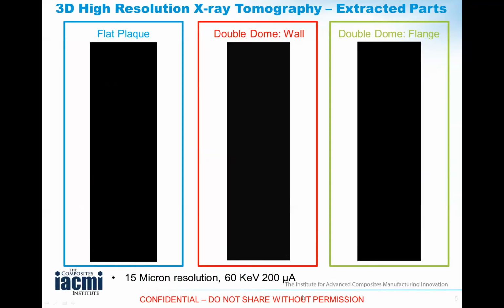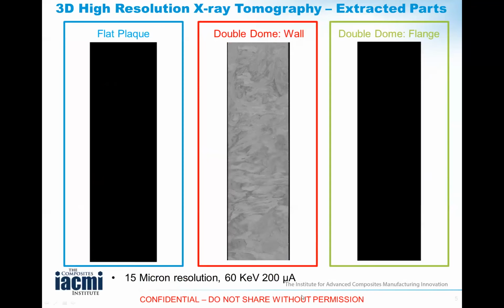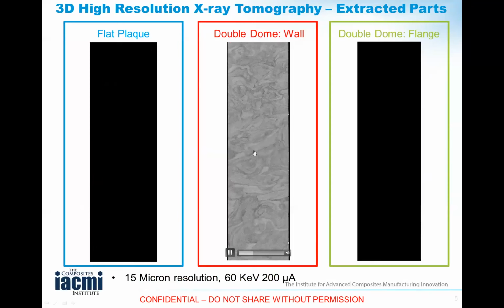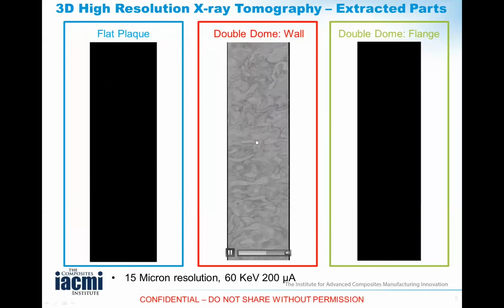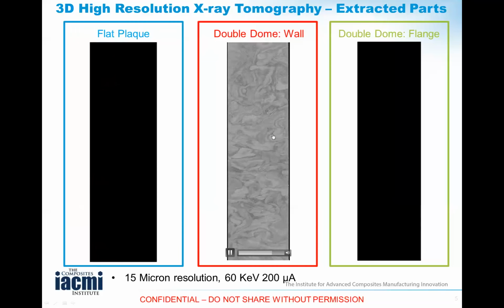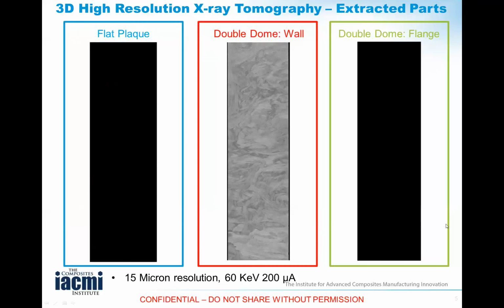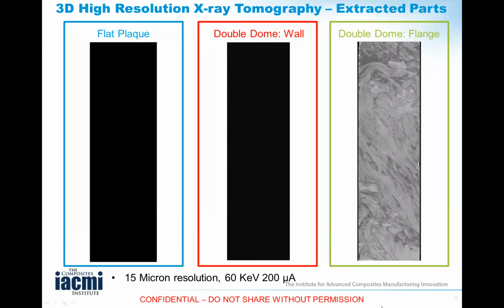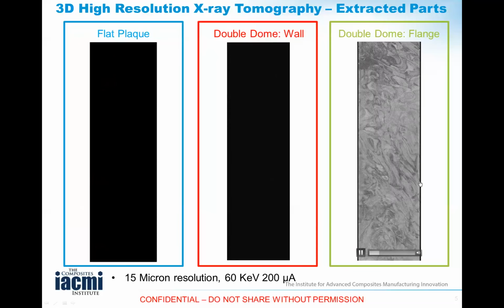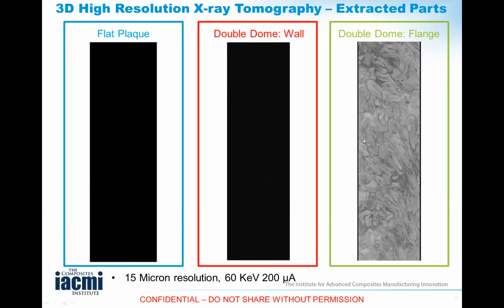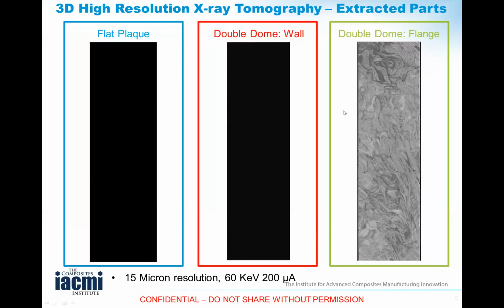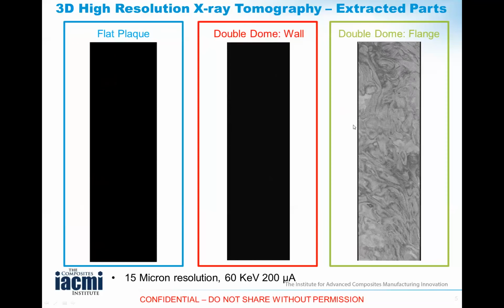If I play, on the other hand, the same microstructure for the wall right now, you can see fundamentally that there are certain zones of preferential orientation of these platelets depending on the flow of the charge pattern. And similarly, if I were to quickly show you the fiber orientation in three dimensions for the flange part, you could see that more or less there is a preferred orientation at 45 degrees.